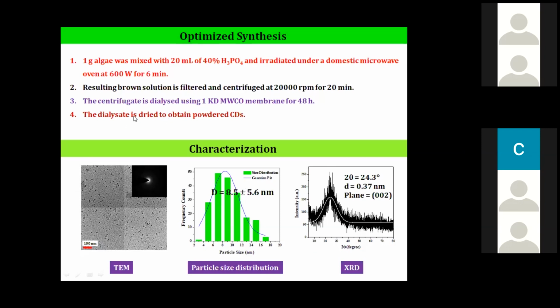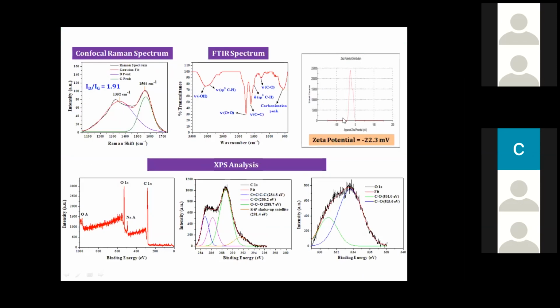And you can also analyze the material by X-ray, and also look at the XPS analysis. One can look at what is the composition of all this material. So we go for Raman analysis, confocal Raman, to find out what is the ratio between the diamond-like carbon and the graphitic-like carbon. In this material, the ratio Id to Ig is around 1.91. Also look at the vibrational spectroscopy to determine what kind of functional groups are present on the surface, and that is how we analyze the IR also.